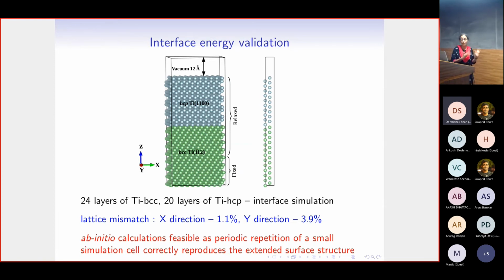Fortunately, at this time we were also working with the interface for the titanium BCC and the titanium HCP system. And it so turned out that for the particular orientations we had chosen for the titanium HCP and BCC solid-solid interface, we were able to work with a very small simulation cell, as shown here, using the ab initio method. If I repeat this structure along the x direction and the y direction, I am able to get back this structure. So it has a periodicity in the x and the y direction.